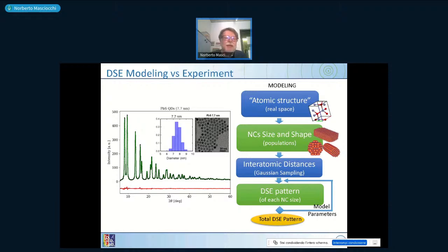The fit can be then expressed in terms of this histogram, and the histogram is centered about 7.7 nanometers and has a certain width. If you now compute the size distribution from TEM, these are the materials which are given. This is a very tiny portion of our material. You can image this by TEM, you can make a histogram and compute the same 7.7 nanometers system.